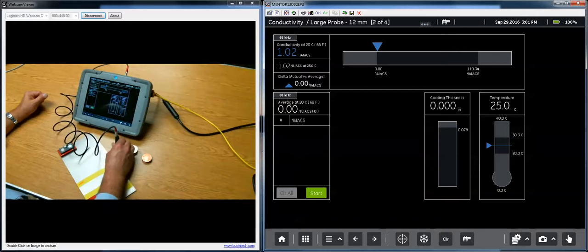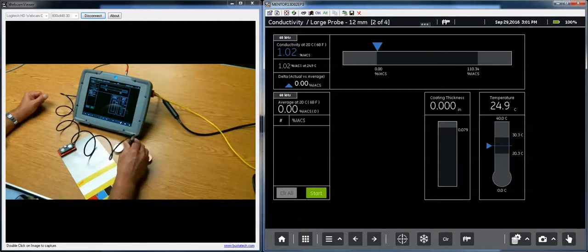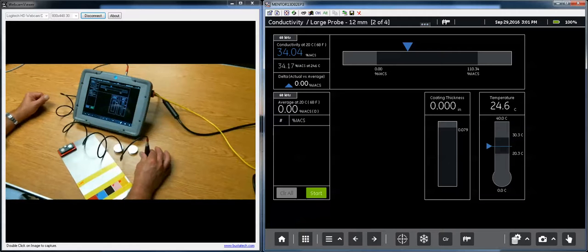Titanium is one of the few materials that's down in that range of conductivity, very low in conductivity. I have a random aluminum sample here at about 34. And I have a copper alloy here that should be right around 100,